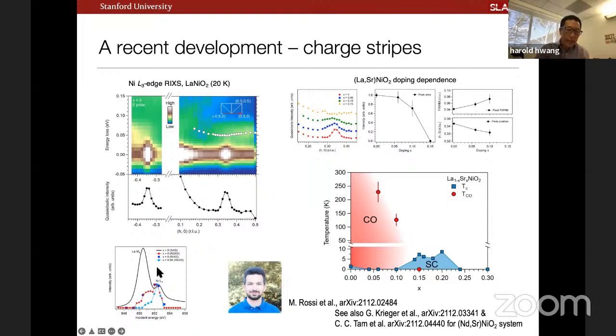It's interesting that as we look at the undoped, in this case lanthanum nickelate, and we look at this resonant scattering, you see contributions both at the nickel L edge as well as a lanthanum M4 edge. But as we dope into the hole-doped and superconducting direction, this projects primarily to the nickel lattice. So we have apparently a charged stripe.